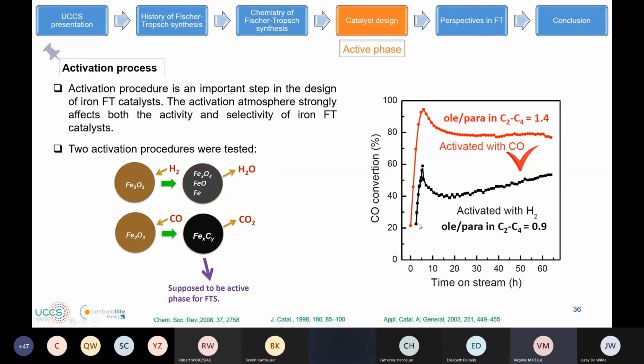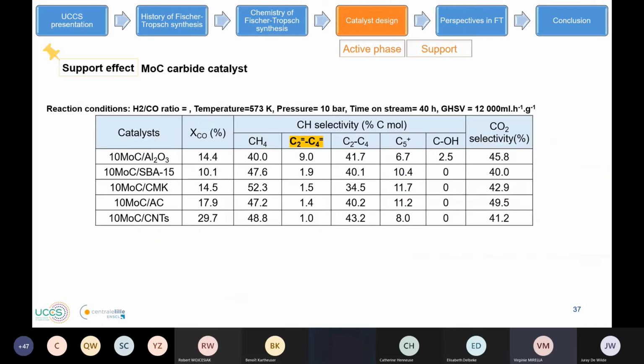In comparison, the catalyst that had been treated with hydrogen did not lead to the formation of the carbide phase, but to the formation of metallic species. And then we observed a slow increase in the activity, a slow increase in the conversion of CO. And this slight increase is probably due to the formation of carbide phase during time on stream. And of course, the olefin activity was a little bit less. So the activation process is really important to improve our selectivity to our desired products.